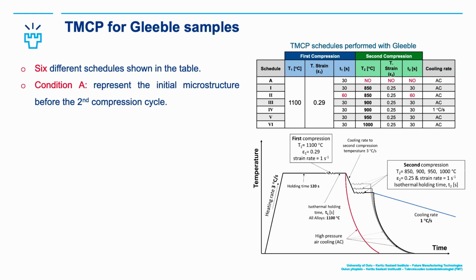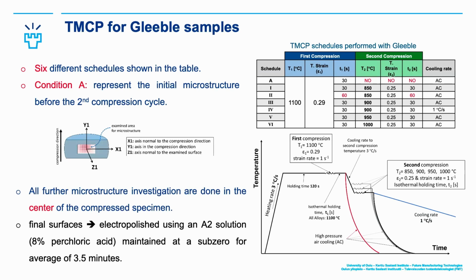It's also worth mentioning that the second compression for all of the schedules has a true strain of 0.25. To see the effect of longer holding time, from this curve we can see that we have a holding time of 120 seconds for homogenization, then going for the first compression, then cooling at a cooling rate of 3 degrees Celsius per second, then getting the second hit, then using airflow as air cooling inside the Gleeble simulation. All of our characterization was done at the mid section of our samples, and for further investigation, all the samples were prepared with a final step of electropolishing, so we could remove 100 to 150 microns of the layer and avoid any stress-induced layers from traditional mechanical polishing preparation.